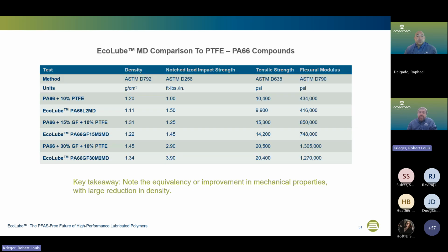Next page is the mechanical property profile of the same items listed on the previous slide. Note the near retention of mechanical properties, especially in the glass-filled grades. In this case, there's a small loss of stiffness and strength, but an increase in impact properties. So if you're comparing these two.